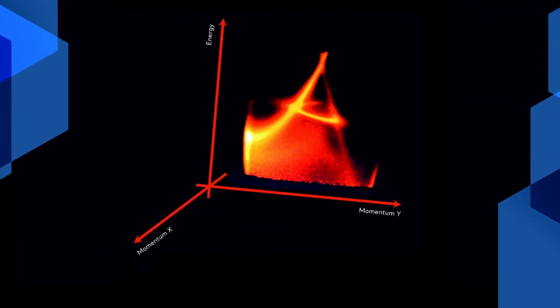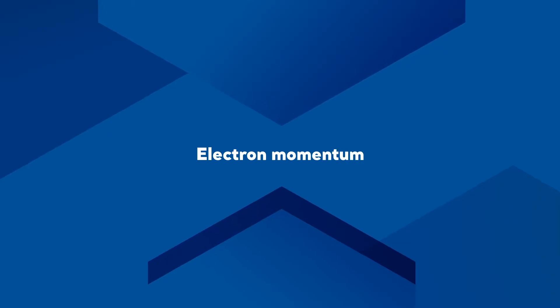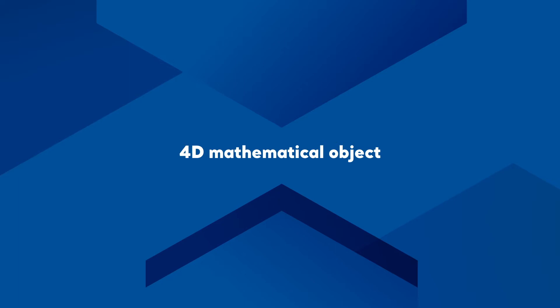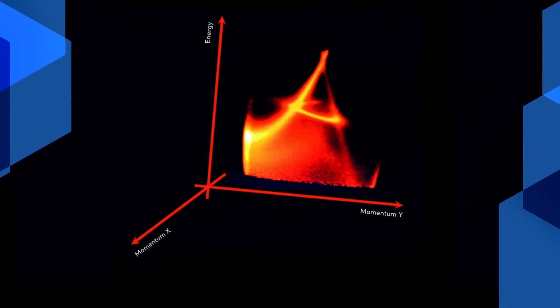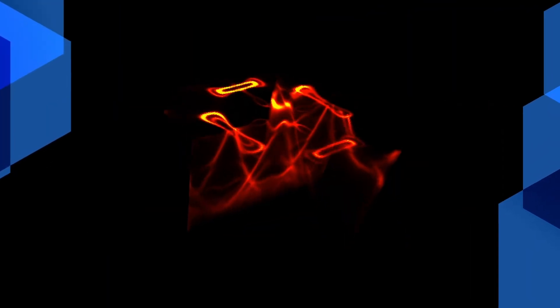Looking broader, we have many different bands. These objects are in fact multidimensional. The electron momentum is a vector object; in the general case, it is a 3D vector. Thus, the full dispersion relation is an unimaginable four-dimensional mathematical object. Fortunately, one can still imagine complete dispersion relations for 2D materials like graphene, where the electron momentum is a 2D vector. Using the third axis for the electron energy, one may represent the complete dispersion relation as a geometric feature residing in a 3D quantum numbers space.